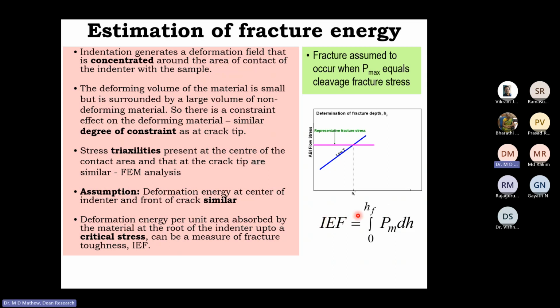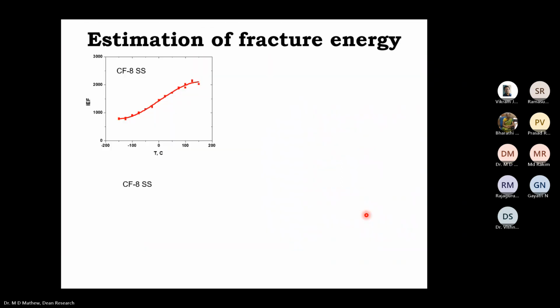So the indentation energy to fracture can be correlated with, for example, the Charpy energy. A lot of experiments were done on CF8. CF8 is a cast version of 304 stainless steel. So ball indentation tests were done from minus 150 degrees centigrade to plus 150 degrees centigrade on this material, and the indentation energy to fracture that I described earlier was evaluated. And this shows how IEF changes as a function of temperature.